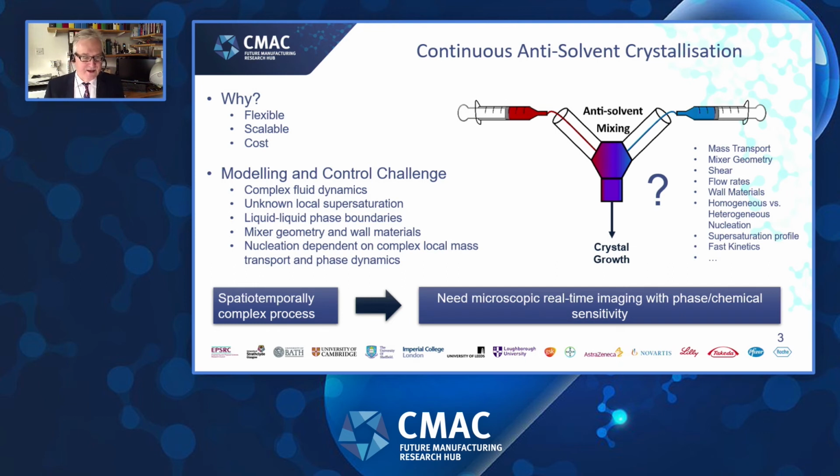The overall aim is to have flexible, more scalable, more cost-effective ways of making crystals. The challenge is that we need to understand the fluid dynamics. For example, we don't know what the local supersaturation is in these systems. We need to understand liquid-liquid phase boundary influences, the influence of mixer geometry and wall materials, and the local mass transport and phase dynamics.